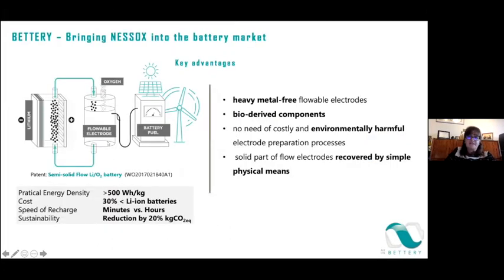Well, the practical advantage of this technology is for sure the energy, which we already demonstrated to be higher than 500 watt-hour per kilogram. And the cost related to the energy can be 30% lower than that of lithium-ion batteries. But there is also another unique advantage. Indeed, we can recharge this battery by plugging it to the grid, but also physically. I mean, we can quickly substitute the slurry, like refueling our system. That brings the speed of recharge to minutes instead of hours.